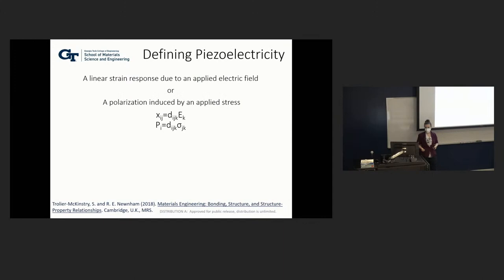So what is piezoelectricity? Piezoelectricity is a polarization that is induced by an applied stress, or vice versa, a linear strain that is induced by an applied electric field. And as a materials scientist, I like to think through a physical representation of this. If I had this tetrahedra here as my piezoelectric material, and I were to apply a stress to the apex of this tetrahedra, what happens is that rather than shortening the bond length for all of the legs, you actually see that the base of the tetrahedra splays outwards. This then creates that difference in the center of positive and negative charge, which is the polarization induced by stress, which is your piezoelectric effect, right?